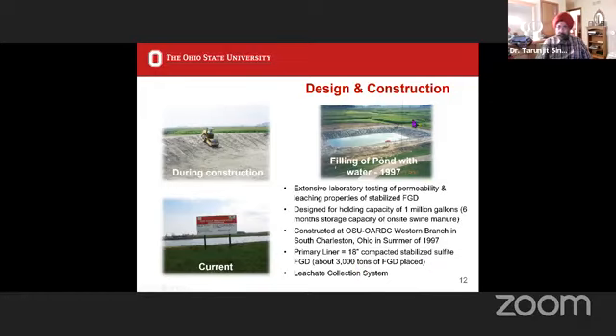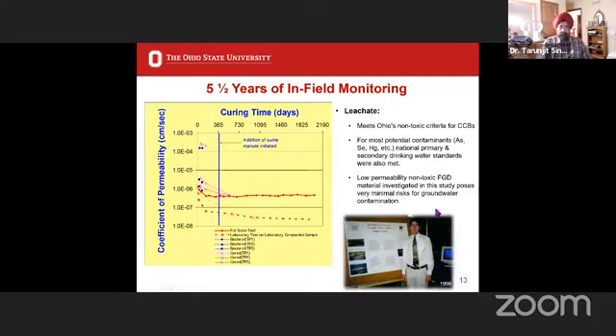Below this facility, there already is a clay layer, because this is a full-scale demonstration project. Between the two, there was a leachate collection system, and here you can see a sump pump. Below this FGD liner and the leachate collection system was about 30 feet of thick gray clay. If we pump the water out of the sump, there's a water differential between the pond surface and the sump. The pond level remains constant. I pump it down in the sump, and if I let it go, the rate at which the water rises is essentially a falling head test. So we were able to replicate that in the field.